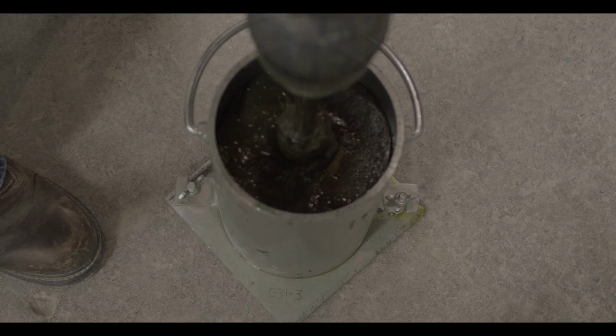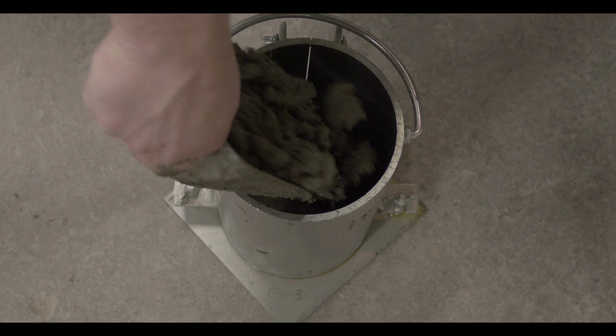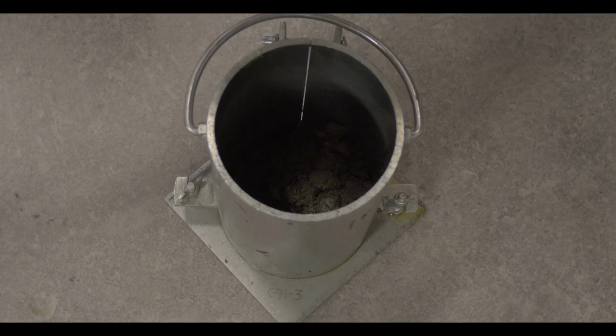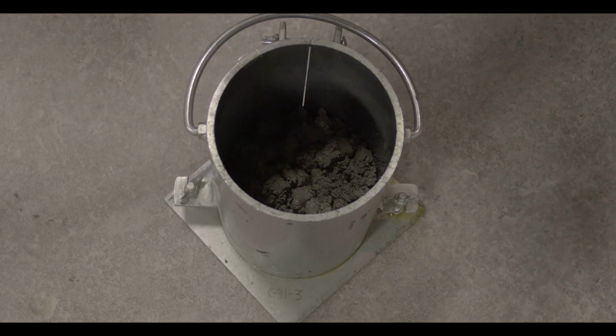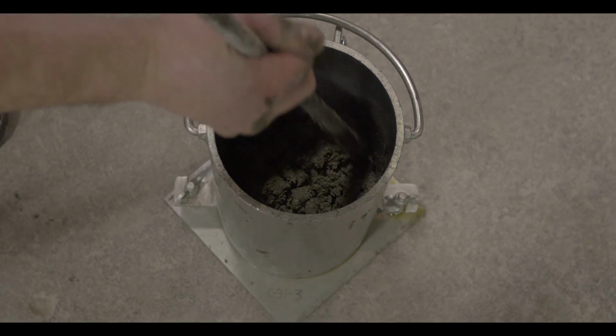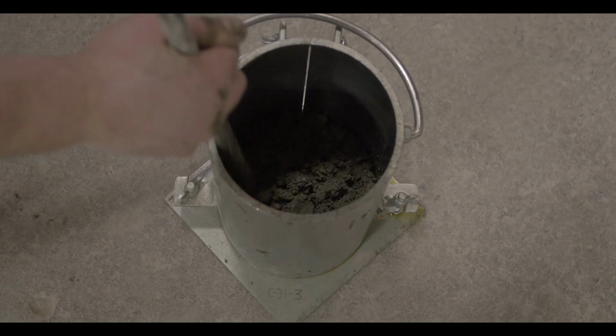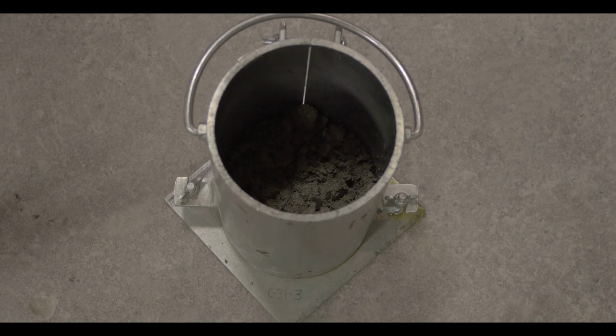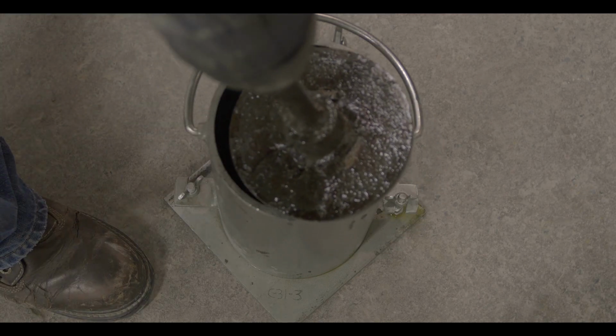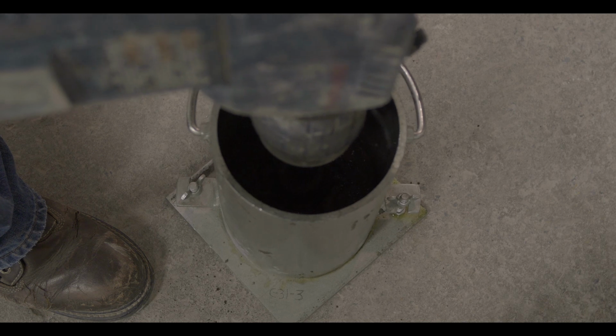Lower the vibrating hammer into the mold to check for proper clearance. Place enough concrete in the mold so that the mold will be filled to 1/4 of its volume after consolidation. Use a tamping rod to distribute the loose concrete as it is added. Place the vibrating hammer with the tamping plate onto the concrete. Start the vibrating hammer and allow the concrete to consolidate under the tamping plate.